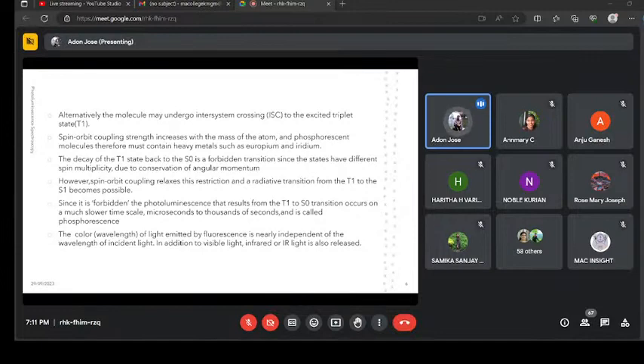In the case of a phosphorescent material, the molecule may undergo intersystem crossing to the excited triplet state. This intersystem crossing, which I am going to explain in the next slide, typically occurs in molecules with a high degree of spin-orbit coupling. That means the coupling of the orbital angular momentum and the spin angular momentum of the electron, which allows the conversion between the singlet and triplet states. Intersystem crossing defines the transition from a singlet state to a triplet state.